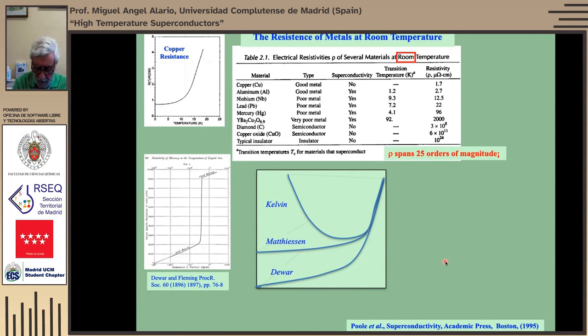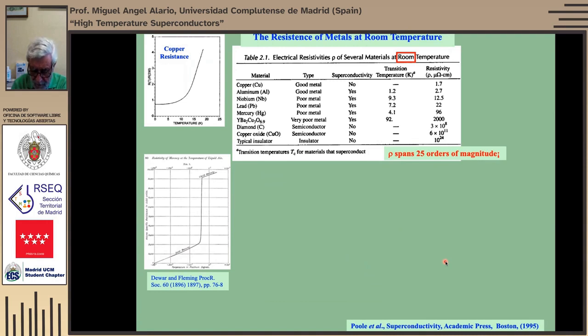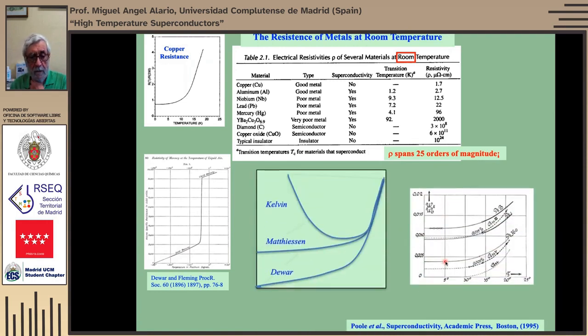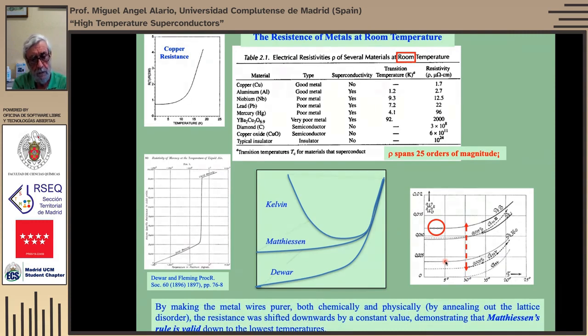And in fact, in the work of Kamerlingh Onnes, which we can show here now, in wires of different metals, he noticed, once he was able to make liquid helium, which was a very difficult problem, we'll see the equipment in a moment, he decided to measure the properties of metals at such low temperatures. And you can see that this is platinum and this is also platinum, but purified. Depending on the purity, the material has a different intercept at the ordinate origin, which is the resistivity. So the resistivity always ends up somewhere, and this somewhere depends on the purity of the material. So it doesn't really get to zero in experimental terms.